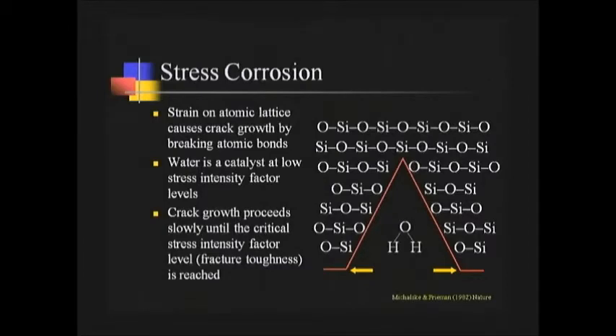And there is some saliva present in the surface of the material, and so some water is coming into the crack from the saliva. And what Steve Freiman showed is that as we bend the ceramic and induce tensile stress on the outer surface, then that crack will concentrate the stress intensity factor and will eventually reach a high enough level that it passes a threshold and has enough energy to split the bonds in between the silicon and oxygen ions, and the crack grows larger. And when the crack grows larger, even under the same stress, we will get a higher stress intensity factor, so the crack will accelerate, growing faster and faster over time.